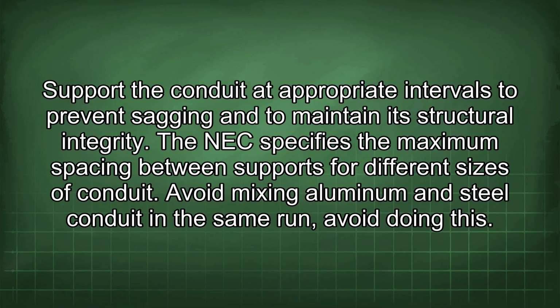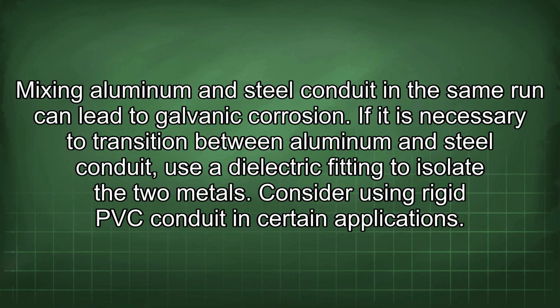Avoid mixing aluminum and steel conduit in the same run. Mixing aluminum and steel conduit in the same run can lead to galvanic corrosion. If it is necessary to transition between aluminum and steel conduit, use a dielectric fitting to isolate the two metals.